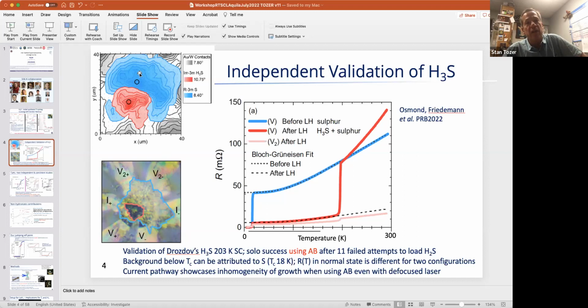But they also found, as you can see in this depiction of the micrograph here, you have the material of interest in red. You've got blue, which is sulfur, and in these gray regions are the electrodes pushing in. And indeed, you look at that and you realize you're only going to see the superconducting material if you look across a couple select electrodes or see it robustly.